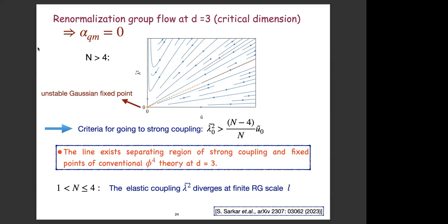And you can basically calculate or find out the value of this lambda, the critical value of lambda, above which we'll have a runaway flow. And next you can consider this case where n is less than or equal to 4 and greater than 1. For this we basically have structural transitions, as we saw in the first case, for the entire parameter space.